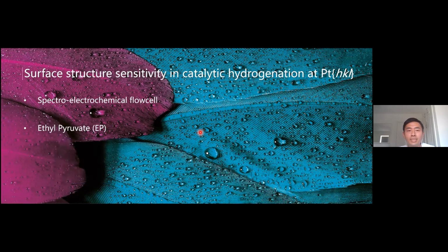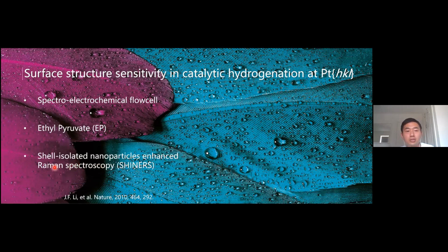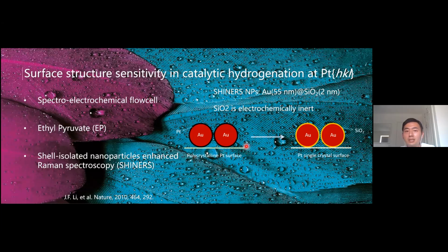Before I started my PhD, the type of shell-isolated nanoparticle enhanced Raman spectroscopy was designed, called SHINERS. These SHINERS nanoparticles were made of a gold core and silica shell, and because silica is electrochemically inert, it doesn't affect the electrode it's deposited on. By replacing the gold-platinum nanoparticles with gold-silica nanoparticles, we'll be able to study molecules interacting with the platinum single crystal surface, and it can boost the intensity of Raman scattering from molecules absorbed on flat surfaces. This was the groundbreaking step.